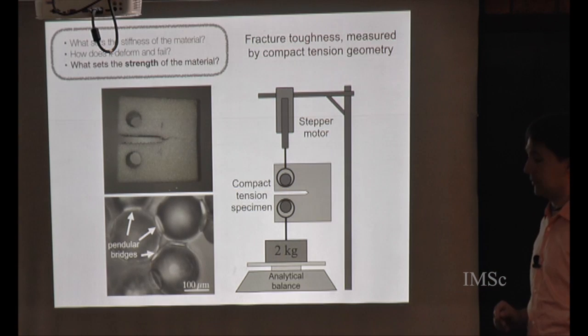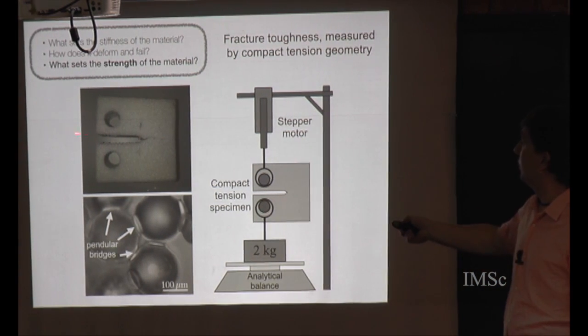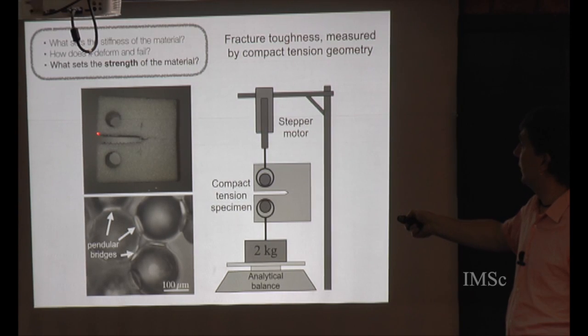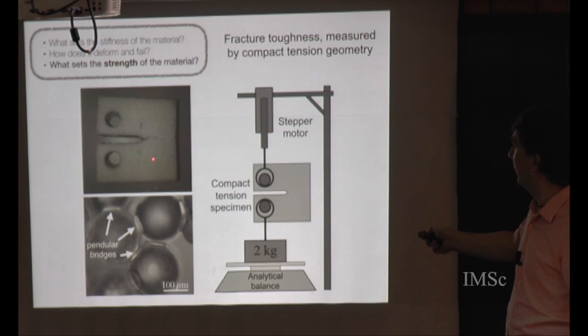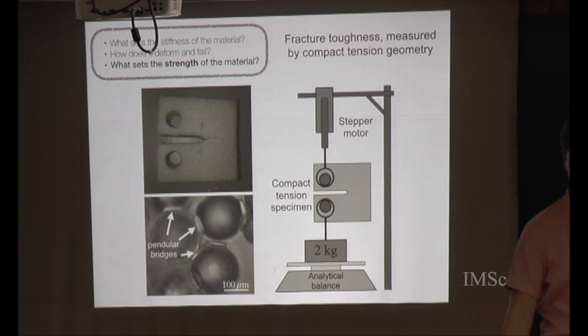And that's the result. You can see there's a crack growing off the surface now. You can monitor as observable the opening of the mouth, and that gives you a proxy for strain, and the stress again is the force applied through here, and that gives you a measurement which can be converted to a stress at the tip. And then you monitor until failure occurs at the tip.